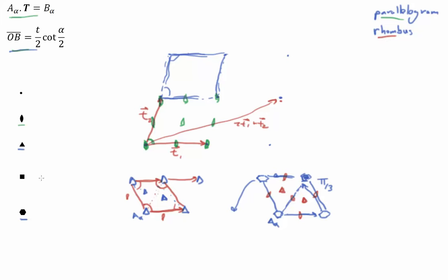So the square, or the fourfold rotation axis, is going to lead to a new two-dimensional lattice. And we can see that if we draw a fourfold rotation axis, a lattice vector, a new fourfold rotation axis. This original axis is going to operate on the new one, rotate it pi over 2 radians up here, and it will be again translated. And all of these lengths are going to be the same. So if this is L, this is also L, this is also L, this is also L. So this is giving us a square lattice.